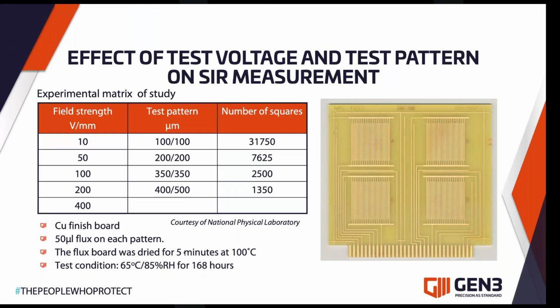We looked at different gapped patterns as well, and we had gaps from 100 up to 500 microns. So the 400, 500 is the B24, and the 350 is close to the B25. The patterns all had the same geometric size, and you can see that the number of squares changes considerably. So we go from 31,750 squares at 100, down to only 1350 with the B24 pattern. And there are some other test conditions there that were principal test conditions for the experiment.